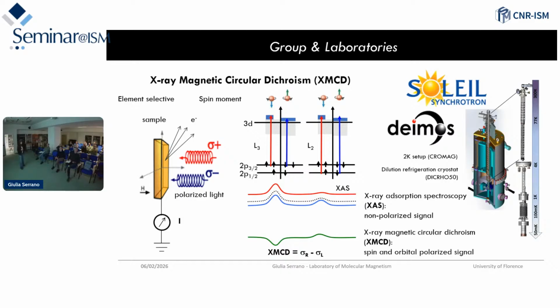This is the place where we most often go for this kind of experiment, in which we can probe our molecular samples, thin films on surfaces, through an element-selective technique in which we hit the sample with X-ray light with circular right and left polarization, and these different polarizations produce a different absorption signal as soon as we have a spin moment and also an orbital moment on the surface.